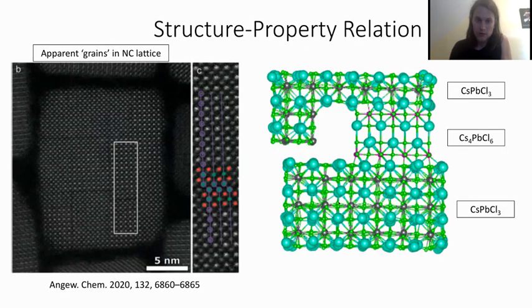And so I was digging around in the literature, or I happened to come across one paper where they saw the same effect as the artificial confinement. So they synthesized a bunch of samples, but varied the amount of manganese in them. So they went from like reasonable amounts to very excessive. And what they found is that once they increased to very excessive amounts of dopant, they started to see a blue shift in the exciton peak.